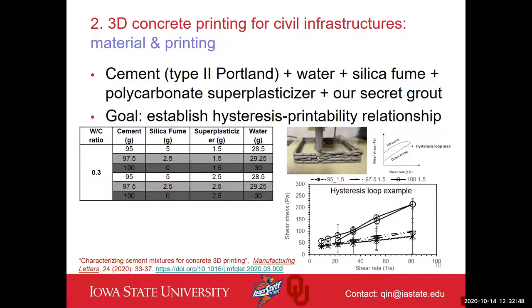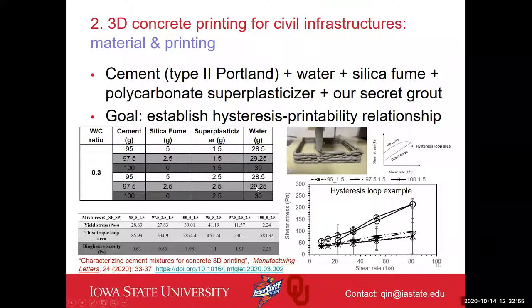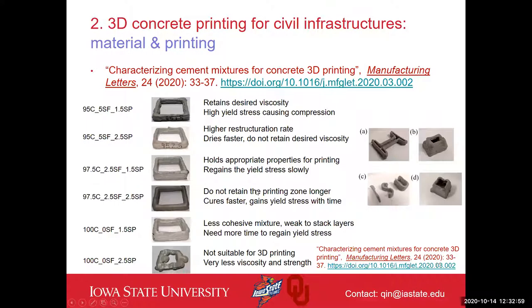This is published in Manufacturing Letters. I posted the link over here; if you want more information, you can find it there. Based on that study, we started to demonstrate how different materials affect the final printing quality. The biggest challenge for us is how to stack up the printed results. We are printing layer by layer, and cement or concrete is very hard to control in solidification, so it's very difficult to stack up each layer. We started with squared hollow structures, only trying to see if they can stack up for future printing. Based on the optimized material recipe, we were able to print good structures.